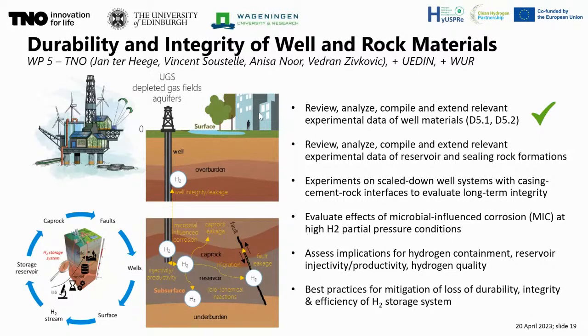Other work planned and ongoing focuses more on the exposure effects of hydrogen on reservoir and sealing rock formations, and experiments on scaled-down well systems with casing-cement-rock interfaces to evaluate the long-term integrity of these interfaces, and in particular microannulus formation as a response to cyclic injection and withdrawal under hydrogen exposure. And Wageningen also has another task here, to evaluate the effects of microbially influenced corrosion at high partial pressures on wells in particular. And of course, what we hope to be able to say, conclude and recommend is the implications for hydrogen containment, reservoir injectivity, production, and quality of hydrogen, and recommend best practices for mitigation of loss of durability, integrity, and efficiency of the storage system.